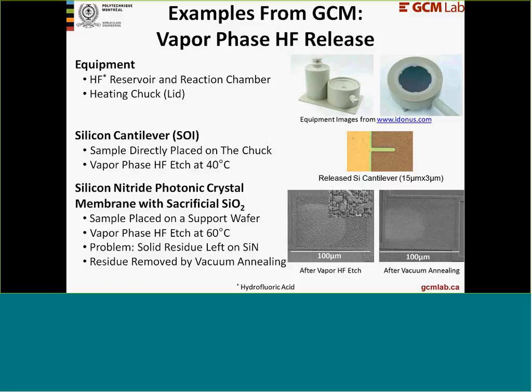Example 2 shows a silicon nitride photonic crystal membrane with a sacrificial silicon oxide layer, processed by vapor HF etching at 60 degrees centigrade on top of a support wafer. The structure has initially been designed for wet etching and critical point drying. As there are some problems encountered in wet etching and critical point drying, vapor phase etching has been tried.